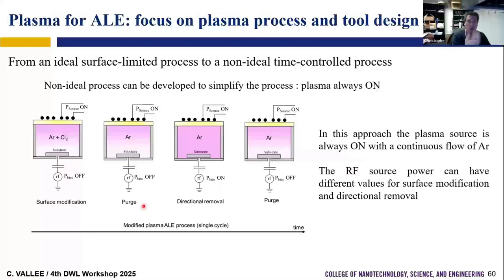So now I will try to show you how we can modify the ALE process to make it more compatible with throughput, for example, what we do in the fab. Instead of having chlorine plasma, argon plasma, and purging in between, we have no purge and we keep the plasma always on. We only pulse chlorine in the first step, argon is always on, and then we pulse the bias. So we pulse both chlorine and bias. That's all we do. So here we have chlorine plasma at low energy because there is no bias applied. And here we have only argon with energy controlled by the bias power. And so we can do the plasma ALE process.